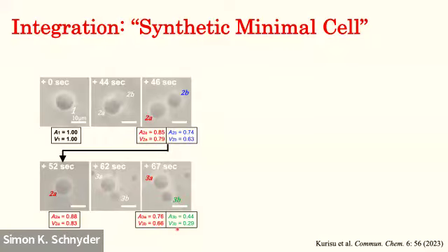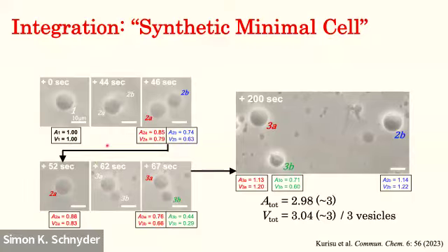have smaller sizes compared to the initial mother vesicle membrane, but by introducing volume recovery processes, by waiting several seconds, these granddaughter vesicles recover their sizes to almost equal to the initial mother vesicle like this. So this is the reproduction, that means growth, deformation, division, and volume recovery of the synthetic minimal cell system.